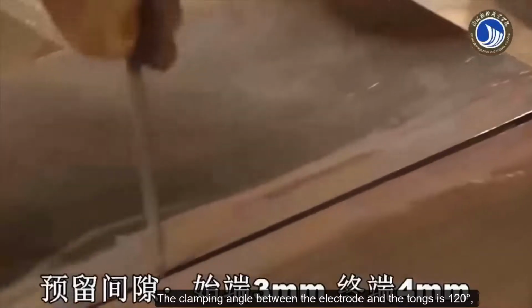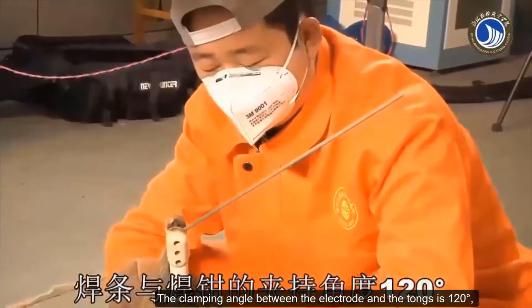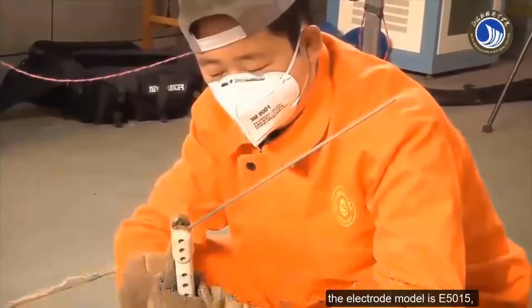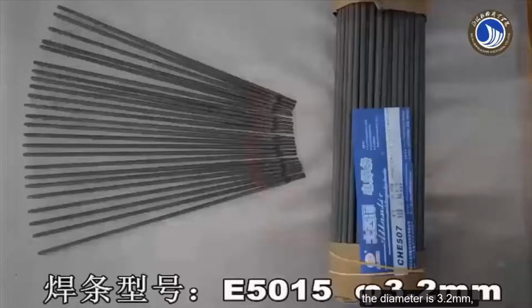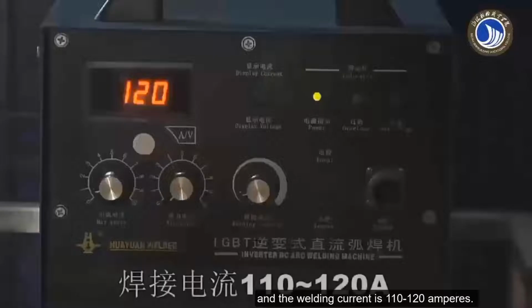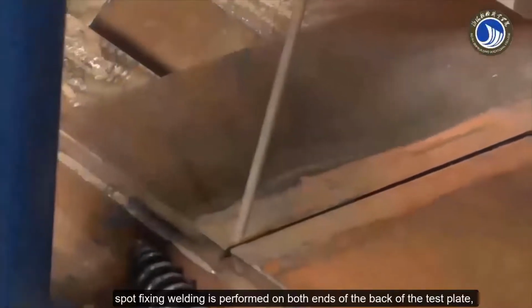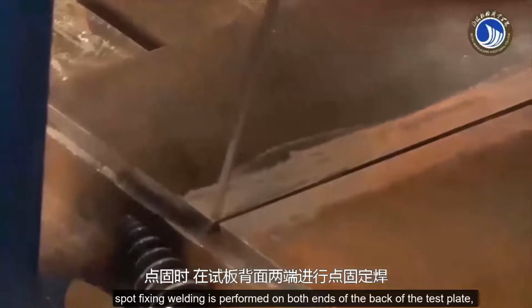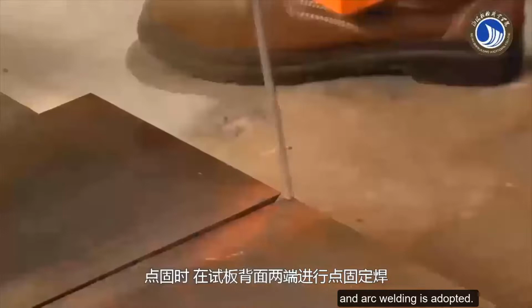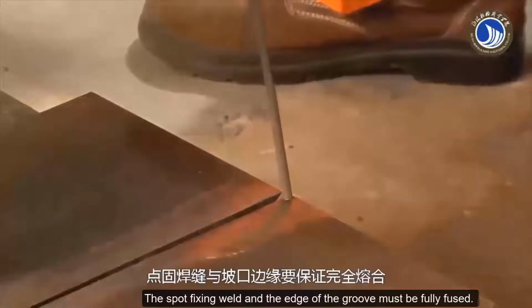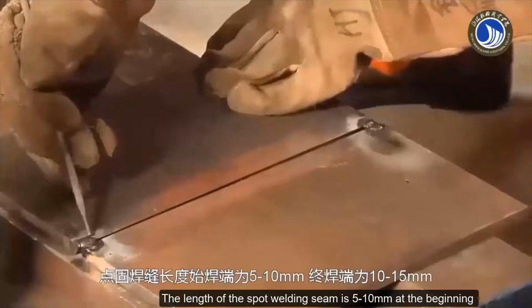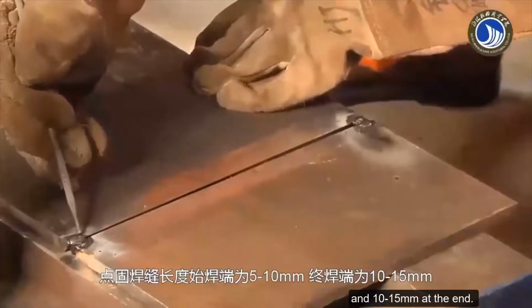The clamping angle between the electrode and the tongs is 120 degrees. The electrode model is E5015. The diameter is 3.2 mm, and the welding current is 110 to 120 amperes. Spot fixing welding is performed on both ends of the back of the test plate, and arc welding is adopted. The spot fixing weld and the edge of the groove must be fully fused. The length of the spot welding seam is 5 to 10 mm at the beginning and 10 to 15 mm at the end.